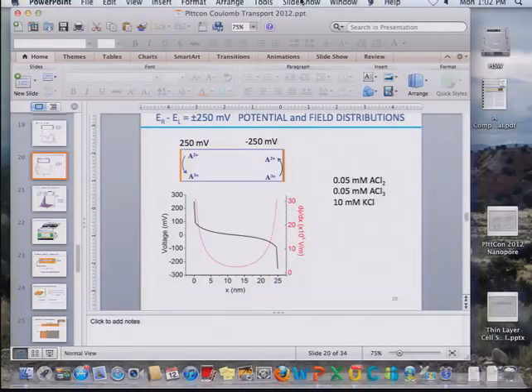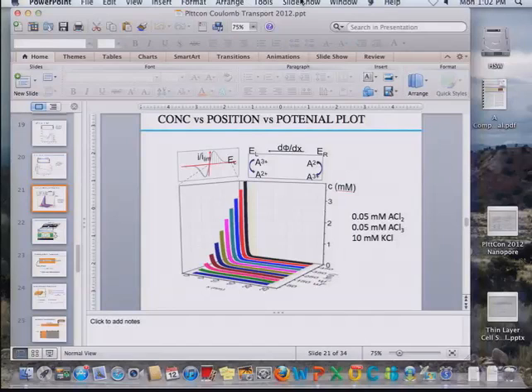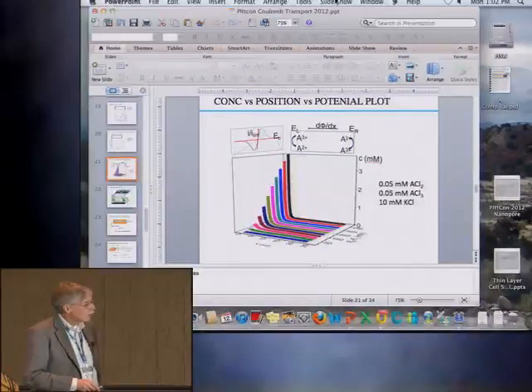But when you put those redox ions in such a narrow little cell, what happens is they all move to one side or the other in response to the electrical field. And you get curves. These are concentration versus distance in the cell. And this is the applied potential for this reaction here. And so this side over here corresponds to this electrode.